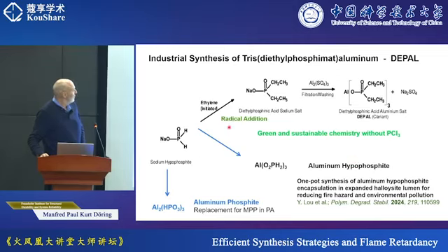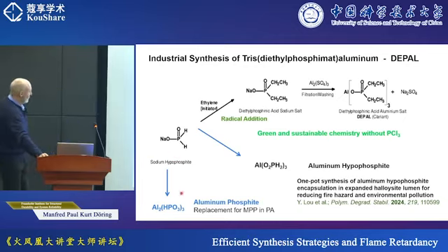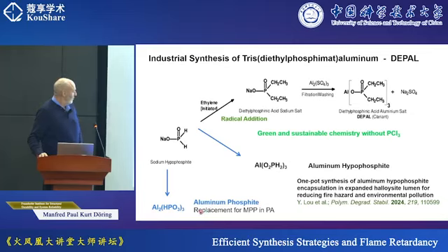It's only a salt formation of that molecule. And nowadays here aluminium phosphite, by a simple oxidation or disproportionation again from here, is a flame retardant developed by Clariant in the last couple of years, and this is a typical replacement for melamine polyphosphate in polyamide.